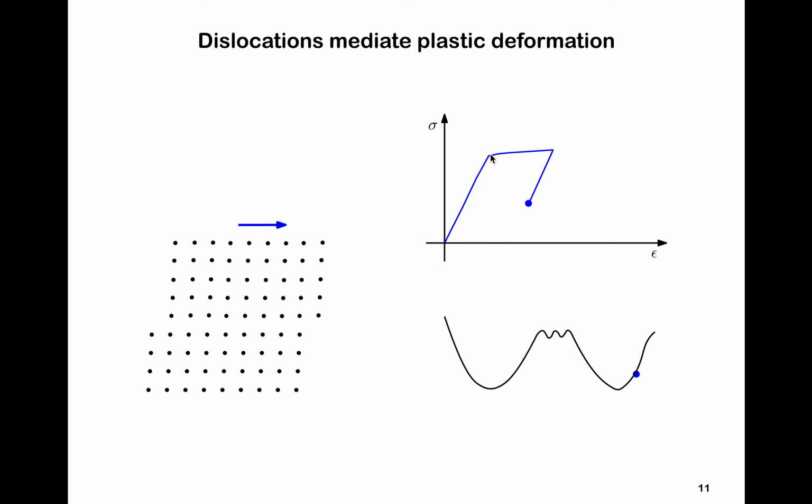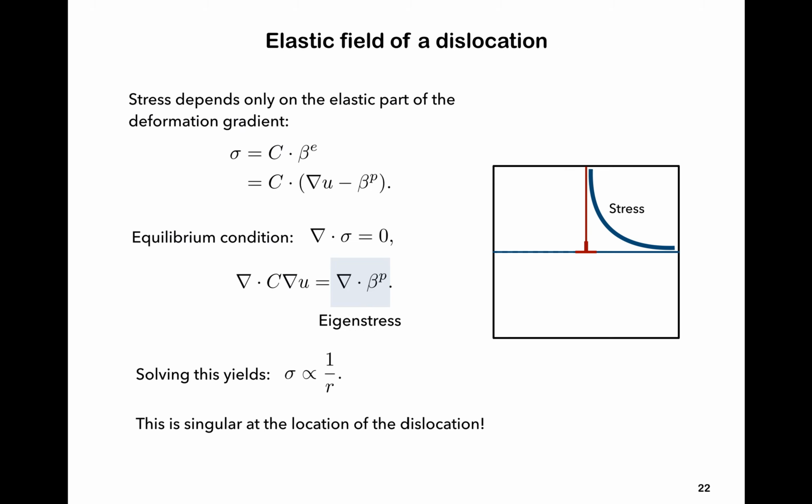If you supply more energy than the bond energy present between two atoms, that bond breaks and the system can no longer be cohesive, and that's why you have a finite upper limit. The macroscopic manifestation of that is precisely what you consider as a yield strength. Okay, therefore beyond the yield strength the system cannot withstand any loads, and yet your classical theory of elasticity is now giving you a result that the stress goes to infinity at the position of the dislocation.